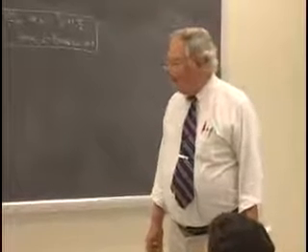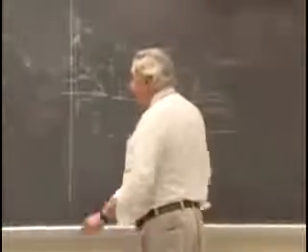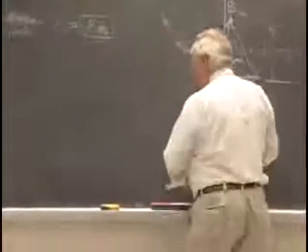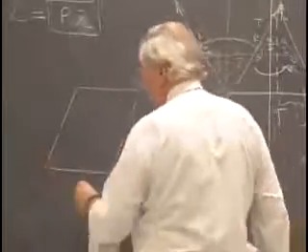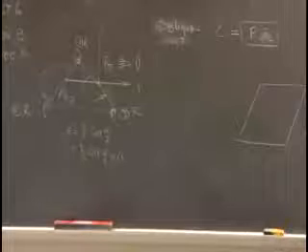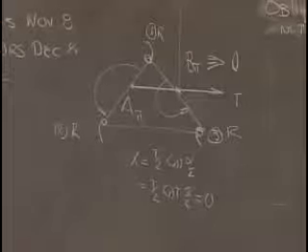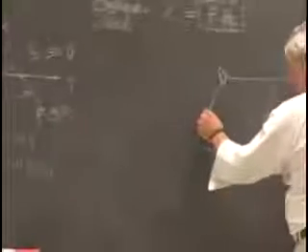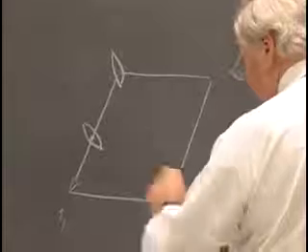Let you catch your breath, and then let's use this to derive the two-dimensional space group, the plane group, that results when we add a twofold axis to an oblique net. It turns out very simply, because if I've got the operation A pi here, that implies that I've got a twofold axis, because that's the only operation that exists within a twofold axis. So I'll start by putting in a twofold axis here. I'll combine A pi with this translation t1. I get a new rotation operation B pi in the middle of this translation. So there's a new twofold axis there.